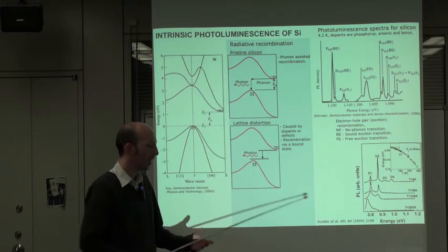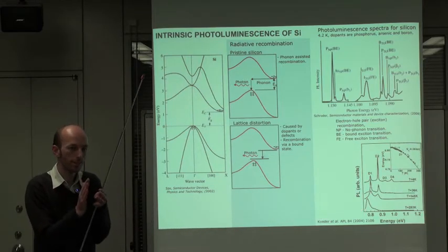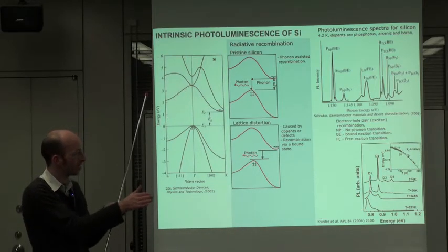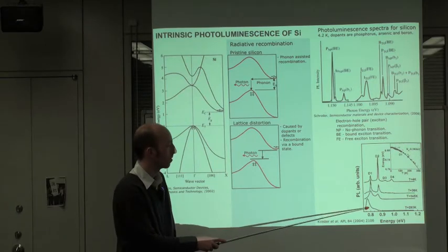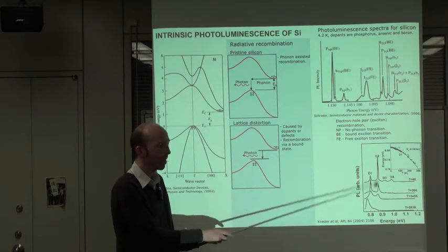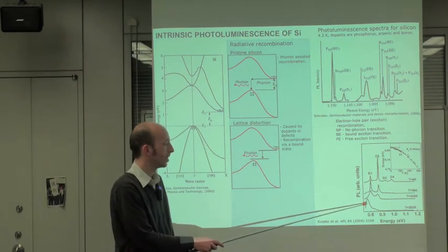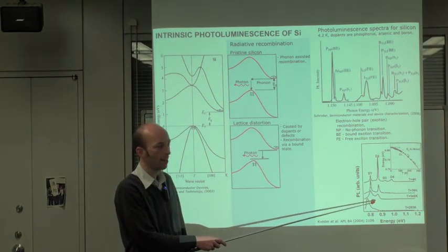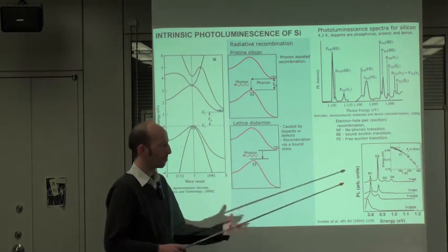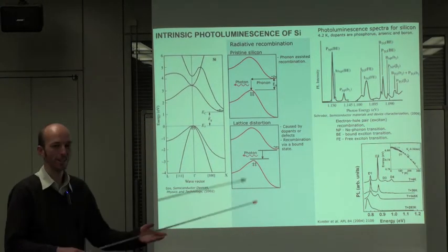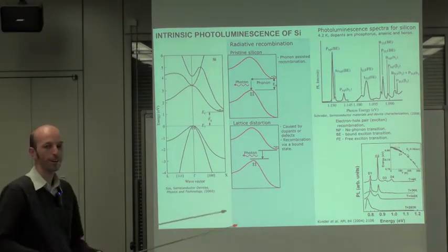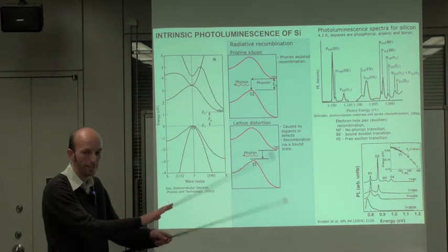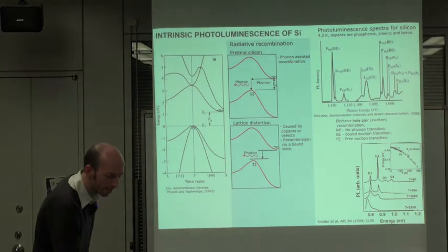These were formed by compressing the silicon to form slip dislocations. So for an LED, this might be a promising way to incorporate miniature lasers onto integrated circuits and have everything made of silicon.